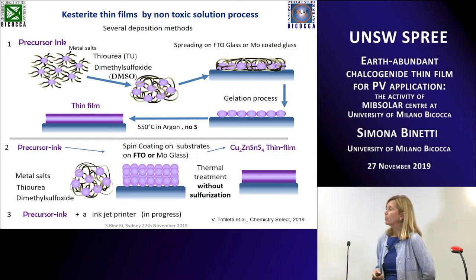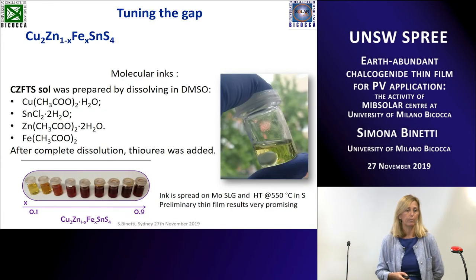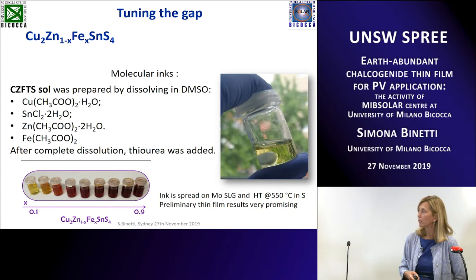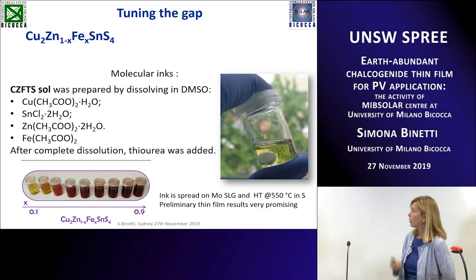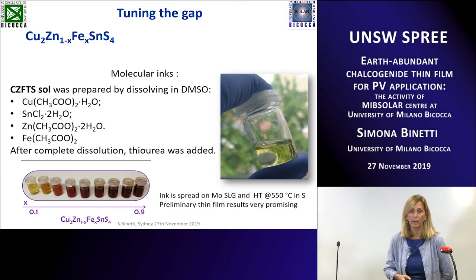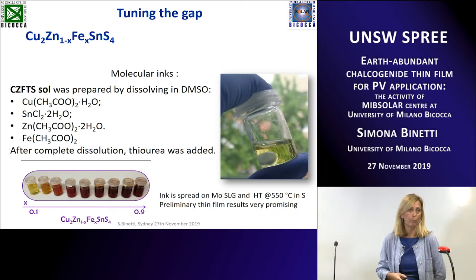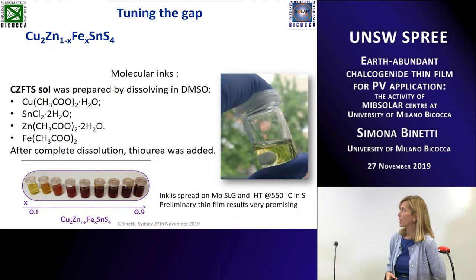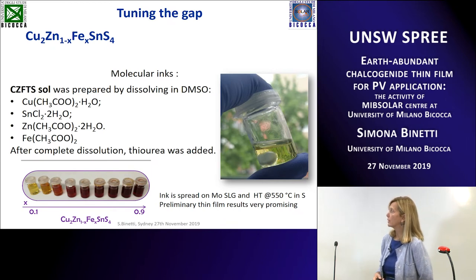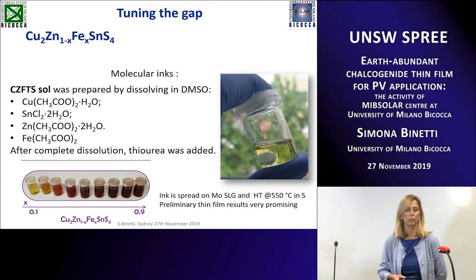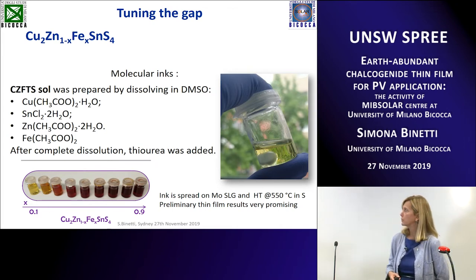Then, by this method, it's possible to incorporate different types of metals or other elements in order to tune the gap, for instance. So we started incorporating iron, and it was very simple because we just have to add iron acetate in the molecular ink, and then perform the same process that I have described before. And we have seen a change in the band gap, and also the quality of the thin film results very promising. There is a change from the Kesterite to the stannite structure according to the iron concentration, and also the band gap can be changed between 1.2 and 1.6.